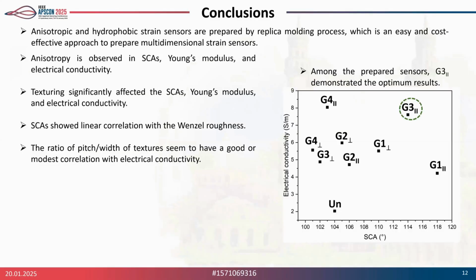So finally, in the conclusion, we demonstrated an easy and cost-effective approach to make a multi-dimensional strain sensor, and it showed anisotropy in contact angles, Young's modulus, and electrical conductivity. The important fact is that the textures significantly affected all those parameters. The contact angles showed a good linear correlation with the Wenzel roughness, and the ratio of pitch by width had a good to moderate correlation with the electrical current. Among all the prepared sensors, G3 parallel to the grooves demonstrated the optimum results in terms of electrical conductivity and contact angle.